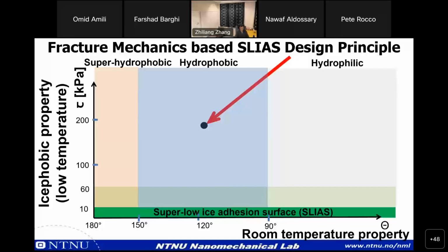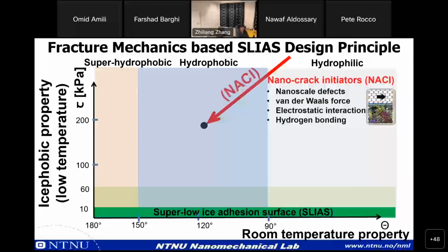So we call this, all the factors influence this curve. We use a name called the nano crack initiator, NACI. That's controlled by nanoscale defects, van der Waals, electrostatic interactions, hydrogen bonding, etc. So the main effect of these nanoscale initiators is to weaken the interface. But no matter how hard you try, it stops at this magic point.